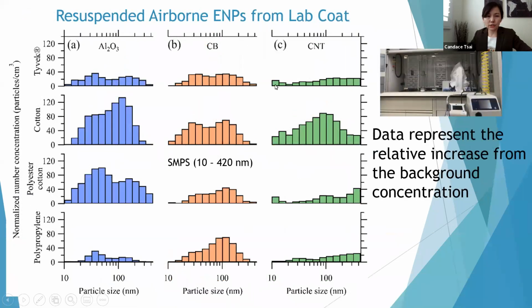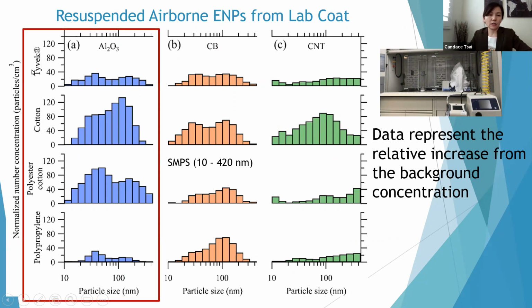So this is the data from the resuspension. After the lab coat is contaminated, as I showed you, the mannequin will be shaken to simulate motion, and we found the release from this process. This is the 30 minute data - we shake it for 30 minutes, and we found aluminum oxide, as expected because of the high level of contamination, releases the highest level compared to carbon black and carbon nanotube. You can see the 4 different types of fabric: Tyvek, cotton, polyester cotton, and polypropylene.